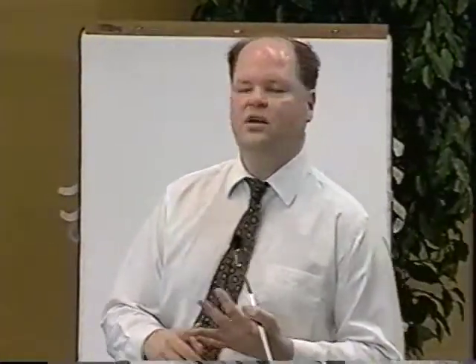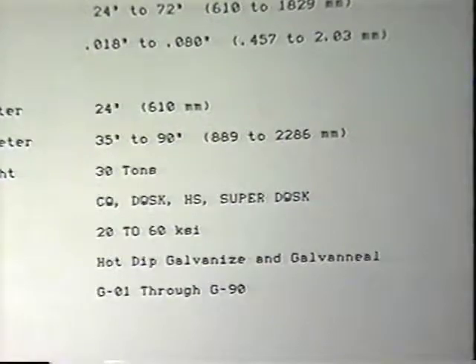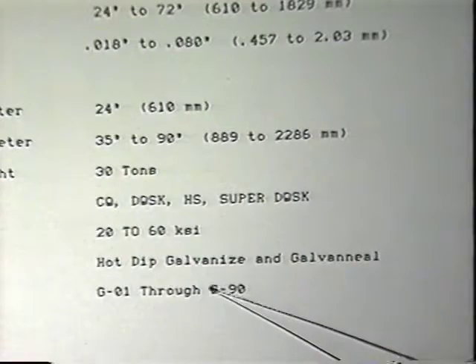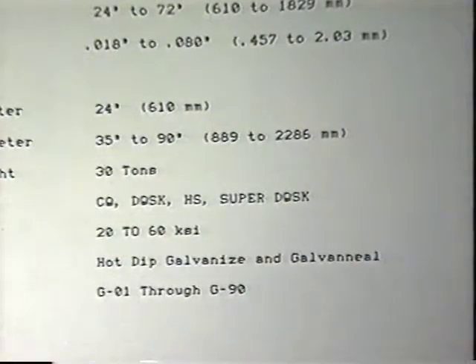For those of you that aren't really familiar with coating weights, there's basically two systems. Just like everything else, there's an English system and a metric system. When you see something that says G90, that's the English system. It's kind of the, I don't want to say old-fashioned way, but that's the way most people are used to talking about it. And what that means is you actually have 0.90 ounces per square foot total on the strip. On top and bottom added together would be 0.90. In that terminology, there's no way to say you actually have 0.45 on the top and 0.45 on the bottom. That's what you're aiming for, but that's not the way you order it. You order at 0.90 total on both sides.